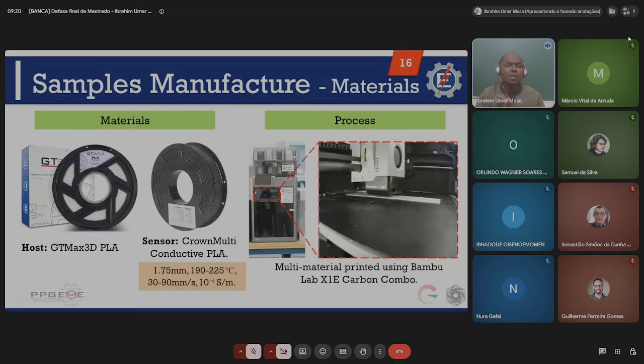And we used a brand of GT Max 3D PLA, white in color, for the printing or manufacturing of the host structure, while a CrownMulti Conductive PLA was used for the sensor material. And of course, the process we used was fused deposition modeling, a multi-material printing process using Bambu Lab model X1E carbon combo.